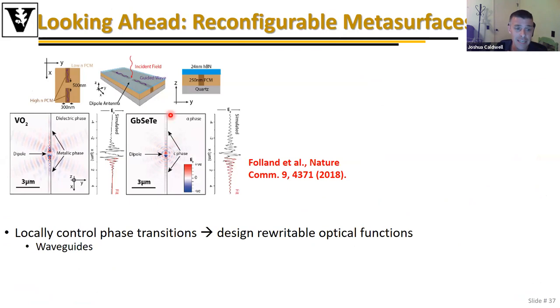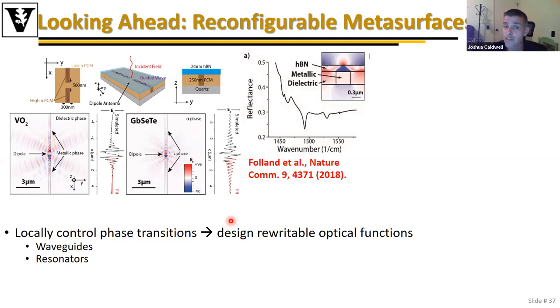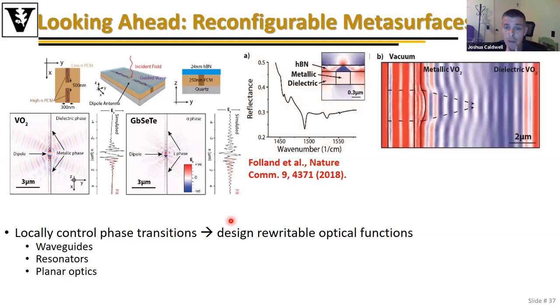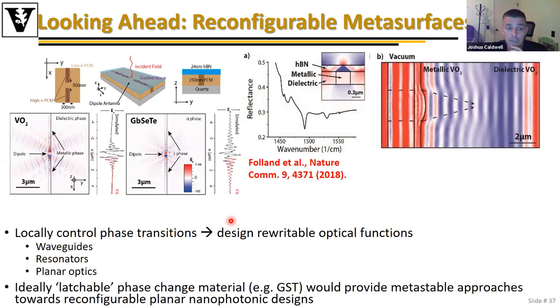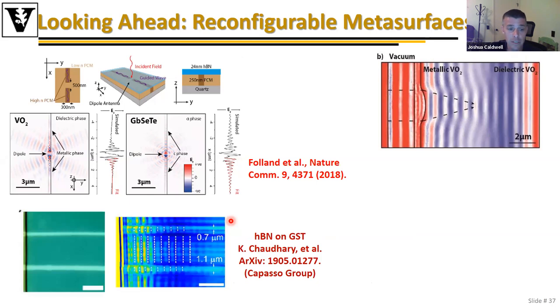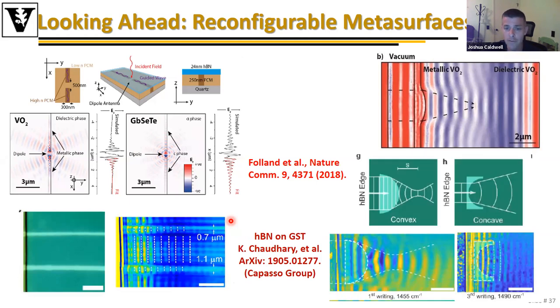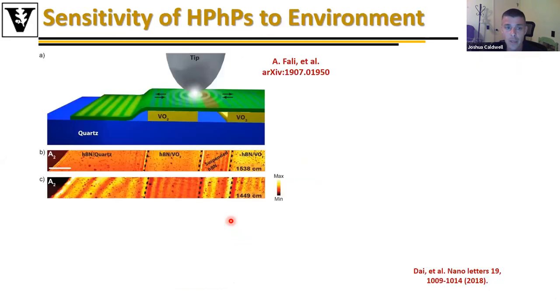right? So for instance, by creating waveguides of material in GST using cubic versus amorphous phase or vanadium dioxide, you can induce an optical waveguide. You could create resonators without having to do any patterning of the boron nitride, therefore saving damage to the system, create lensing effects and things like that. And this was actually experimentally demonstrated not too long ago. Sorry, I should have updated this reference. It's now published by Federico Capasso's group. Here's some waveguides and also some convex and concave lenses in this material.